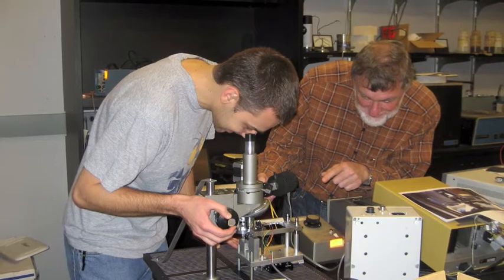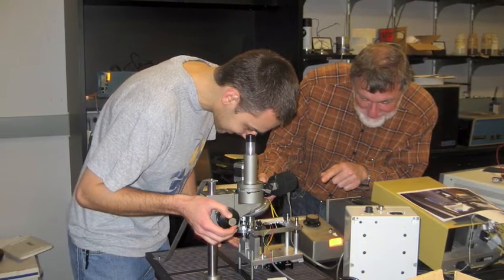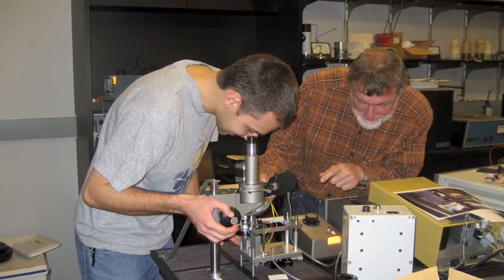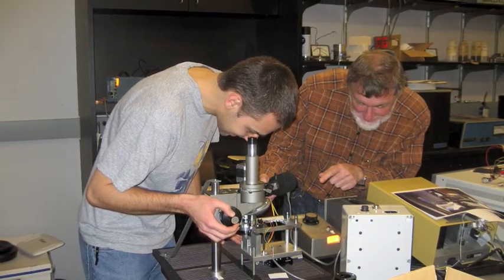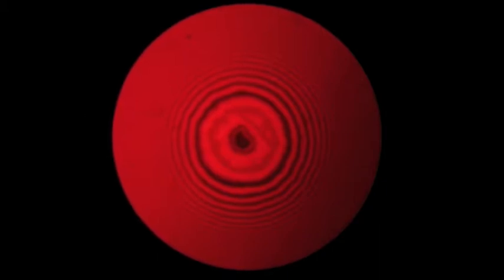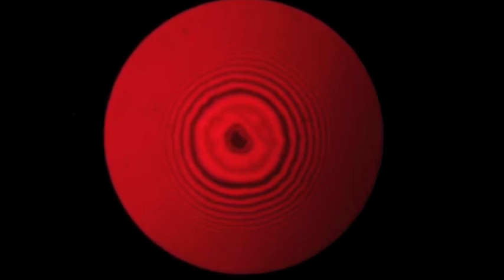Researchers in the high-pressure rheology lab at Georgia Tech study the formation of entrapped pockets of high-pressure liquid in a new instrument dedicated to the investigation of the effect of entrapment on sliding friction. A dent in a hard steel ball, formed by driving a greater than 600,000 pounds per square inch pocket of liquid into the ball on impact with a sapphire plate, is shown in this interferogram. Such dents may be used to texture surfaces for the reduction of friction.